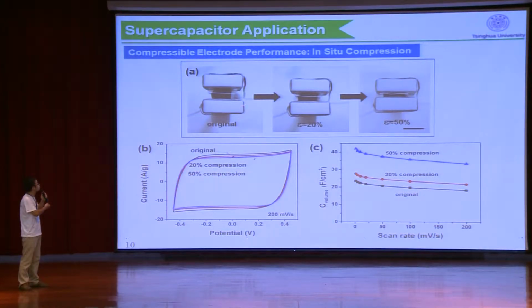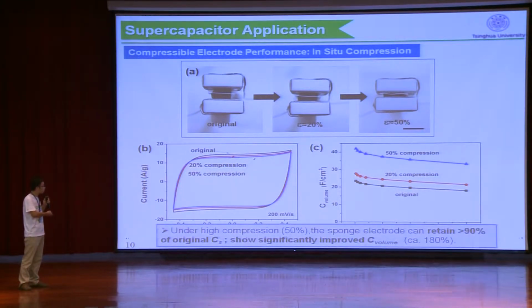And next, we explore its compressible electrode performance. Figure A shows the supercapacitor under in-situ compression. And the capacitor shows similar CV curves under compression compared to the original state. And the sponge electrode under high degree compression can retain more than 90% of the original capacitance, and it shows significantly improved volume normalized capacitance.